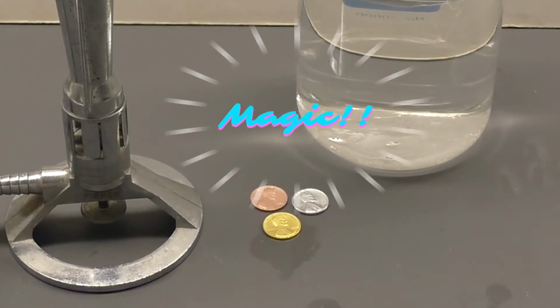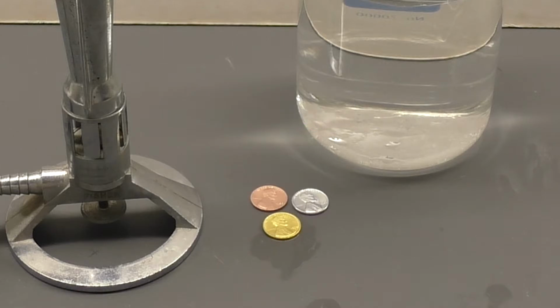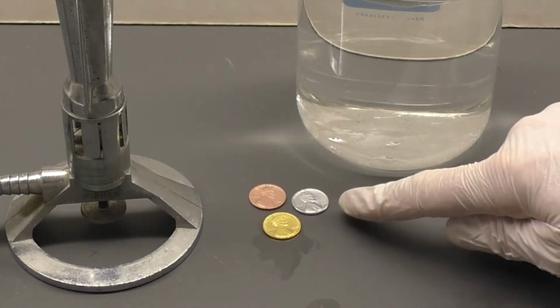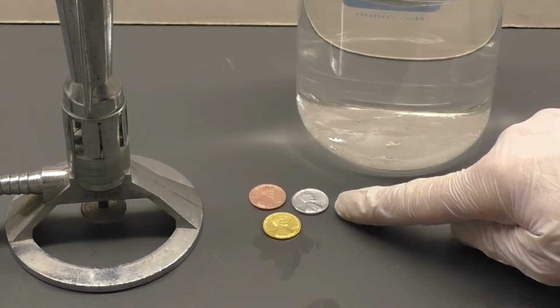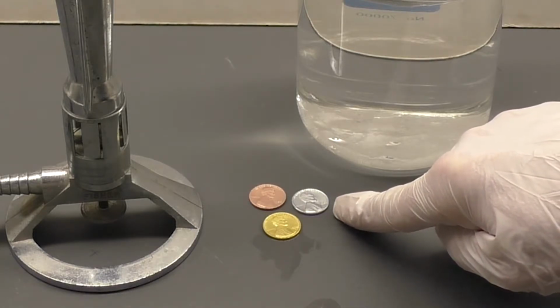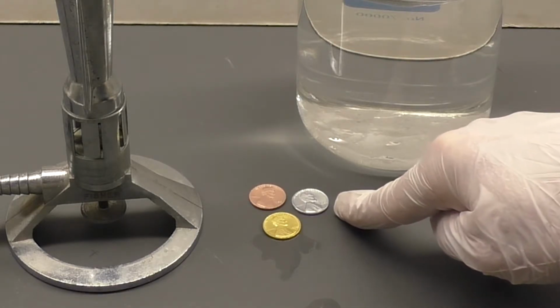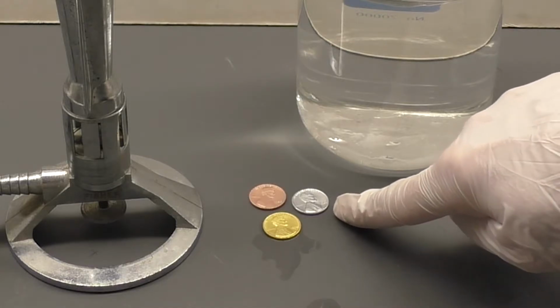Copper, silver, and gold. So, of course, we didn't really transform copper into silver and gold. If you read the background, what we really did was to take copper in the penny. When we put it into the zinc and sodium hydroxide solution, we actually put a coating of zinc metal on the outside of the copper. So that's called plating it, in another way of speaking about that.